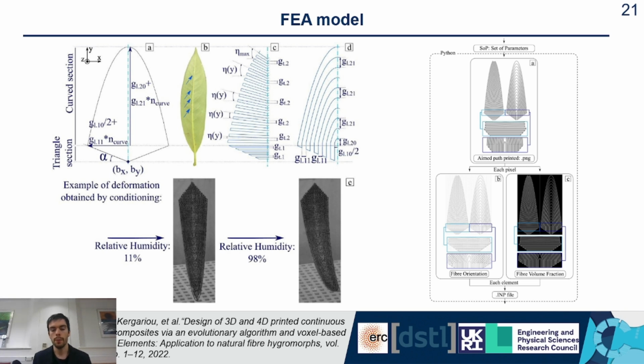So that's our actuator. Then we consider these images of a printing path, and we turn them into images. From these images, we're able to obtain the local fiber orientation and amount of material. And so we could assign to a finite element model the local mechanical properties, actuation properties, and orientation of the fiber to every single finite element in the model. And therefore, we could understand local printing pattern for our model.